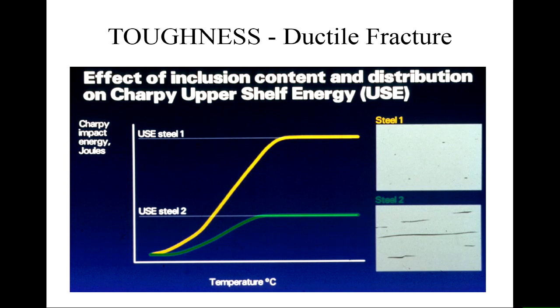And in the primary steel making process, we add manganese to the steel as a deoxidant, but it also reacts with the sulfur to form manganese sulfide. And manganese sulfide is a little inclusion, a little particle in the steel. So in the top case, you can see the grey, which is effectively the steel in this polished cross section, and there are a few dark spots. And those are the manganese sulfide inclusions. And when you've got a few dark spots and lots of spaces between them, that's good. And then we tend to have a quite tough steel. So on the top of the ductile brittle transition, the shelf has a relatively high energy, and that's a good ductile steel.